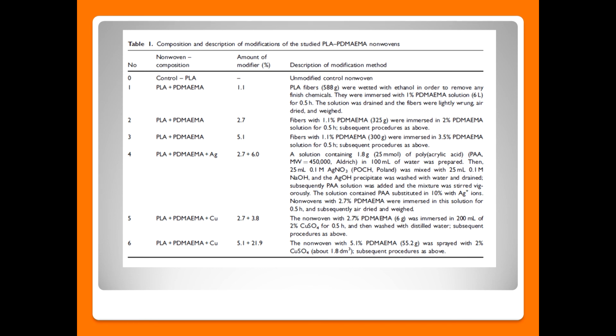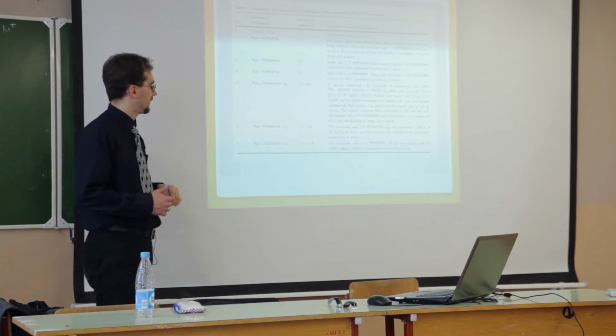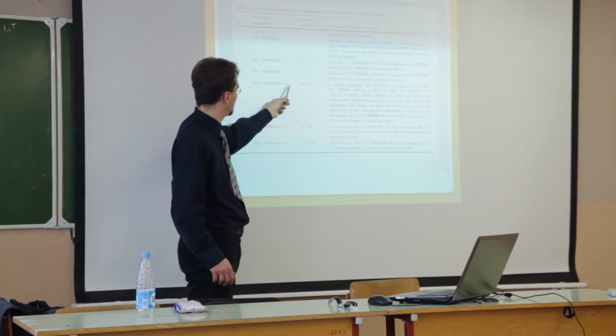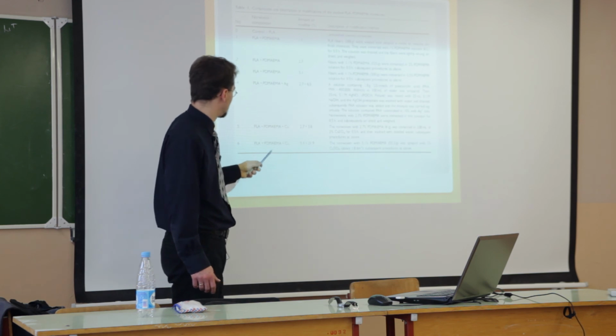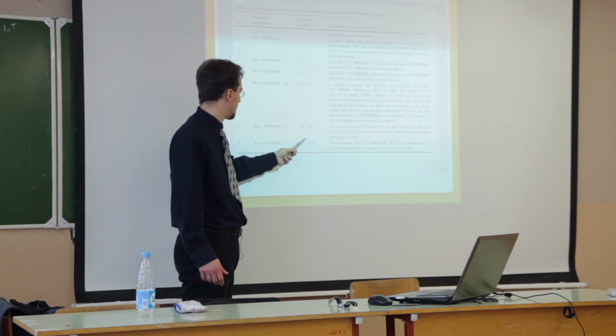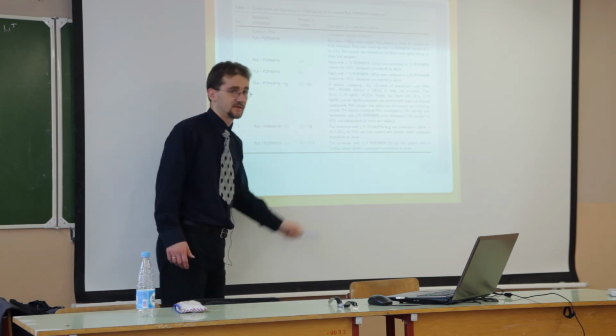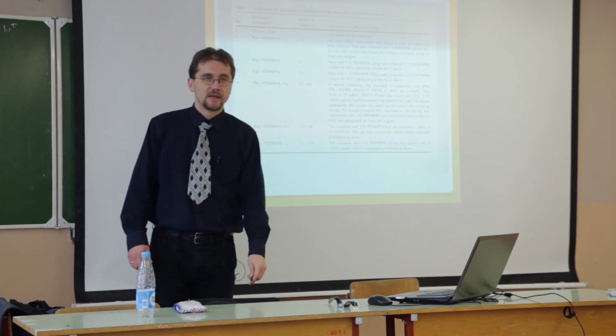To stabilize the surface, to make a complexation between that polymer and some other chemical, we introduced silver in an amount of 6%, or copper in amounts of about 4% and 21%.